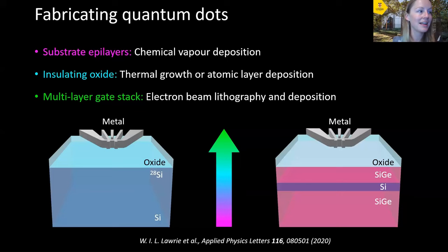And then finally, we can confine our electron spin qubit into these quantum dot devices by tuning the electrical potential of the surface gates. So if you apply a more positive voltage onto the surface gates, you'll attract an electron underneath this gate structure. And we can confine it by pinching off the barriers, by having a slightly more negative voltage on the barriers to repel locally the electrons and just create a small pool of electrons and tune that down to the single electron level.